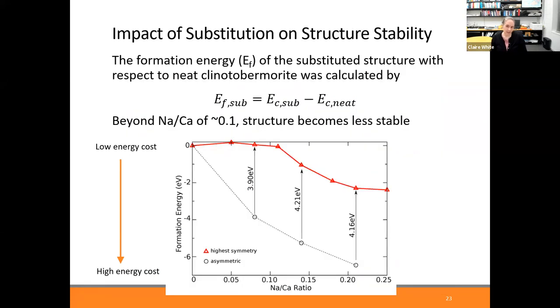What is shown on this slide is that result. And specifically here, this is that energy difference between not symmetric and symmetric for the distribution of the atoms. And what we show here as we go up on the x-axis is with increasing sodium content of the crystal, what happens to the formation energy of the system, which you can think of as an energy penalty to having sodium in some of the locations where calcium originally was in that interlayer region? And the answer is yes, there is an energy penalty, but it only manifests itself after a certain amount of sodium is incorporated into the structure.